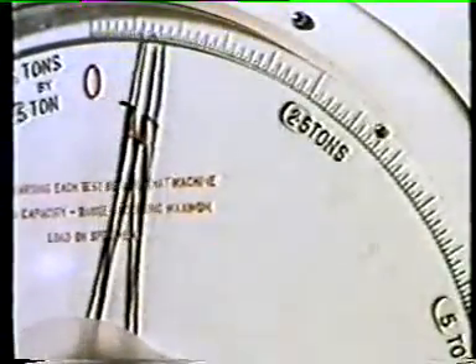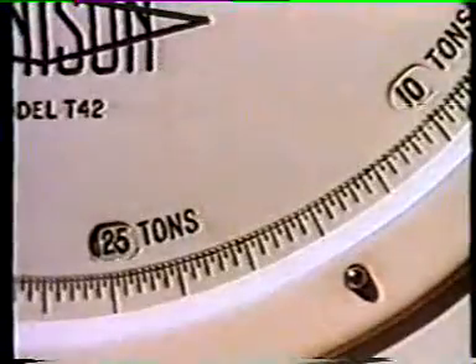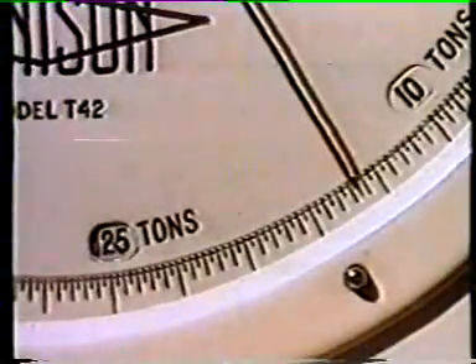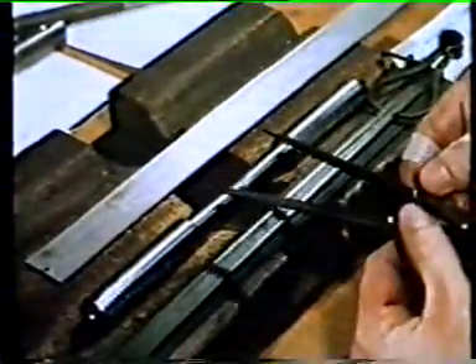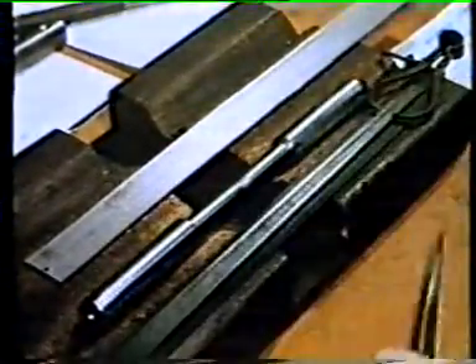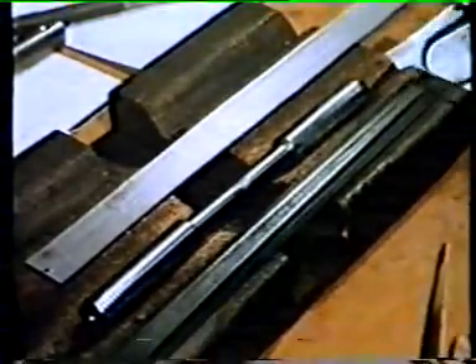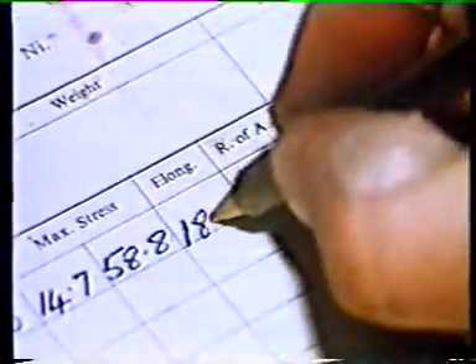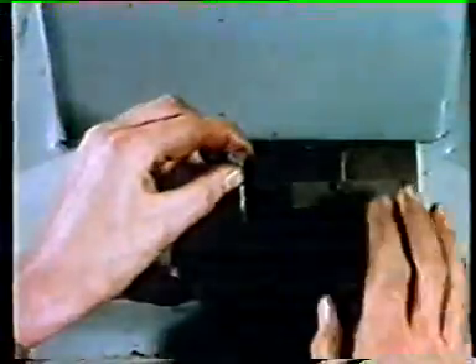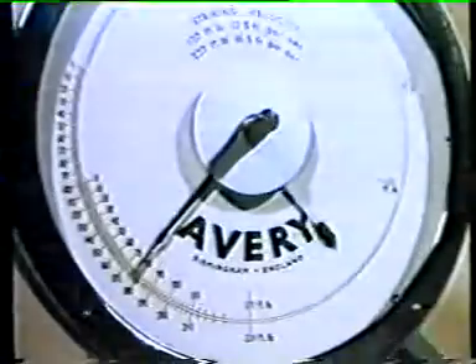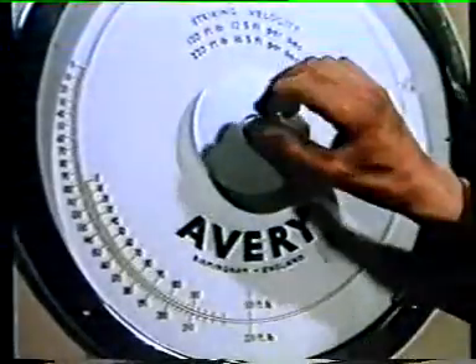This machine tests the tensile strength of the hardened and tempered steel. Other properties are also checked. First, the extent of elongation, then the reduction of cross-sectional area at the point of breakage. There is also an impact test. The test piece has been notched in 3 places at mutual right angles. It is tested at each notch in turn. And if readings show that the resistance is similar at each point, it follows that the properties are even throughout the test piece.